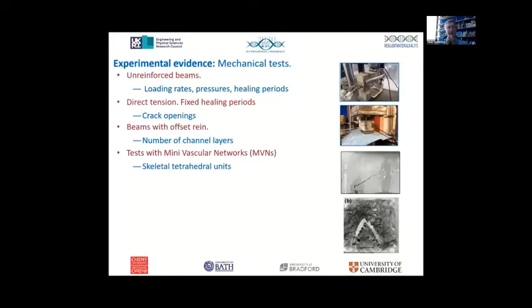Okay, so experimental evidence. Thamish did quite a lot of mechanical tests. We have beams, and we used basically a vascular system because we could know pressure rates, we could know crack widths, and we could observe things at a good scale to provide ourselves with data. So we looked at beams loaded at different rates with different healing configurations, how the crack was when the healing was taking place, different pressures, direct tension specimens where we looked at different crack openings, different healing periods, beams with some offset reinforcement to create some funny shaped cracks. And we have lots and lots of data, courtesy of Christina, on mini vascular networks.